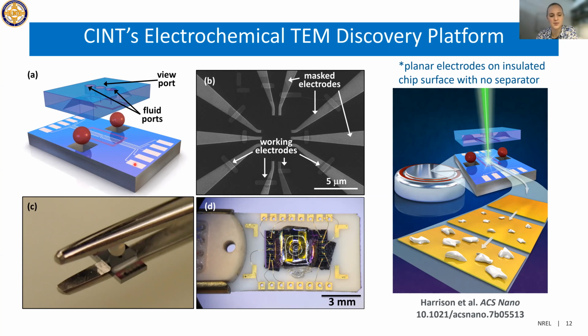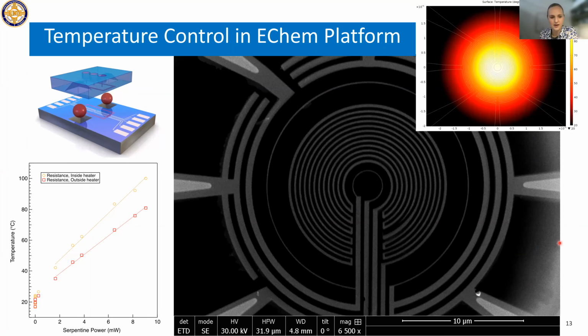So what was really nice about this platform is that it could run very low current experiments. So we were usually at around 2 to 20 picoamps, and then you could run multiple experiments inside the same platform, so you had the same environment around the sample. And so we used this to look at that electrolyte.